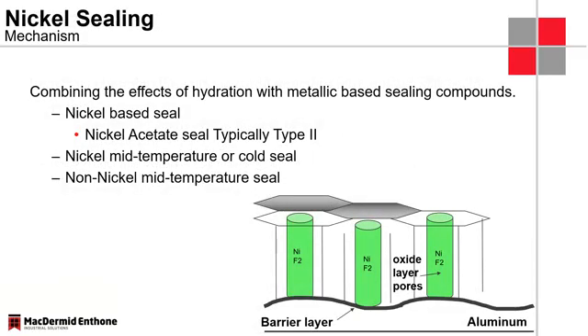This is slightly different to the nickel sealing mechanism. And what we see here is this works more like putting a cork in a bottle. So we precipitate nickel inside these pores, and through that precipitation we will plug the pores, we will close the pores, and really cut it off from any outside attack of the environment. This is for the nickel fluoride, the cold seal.